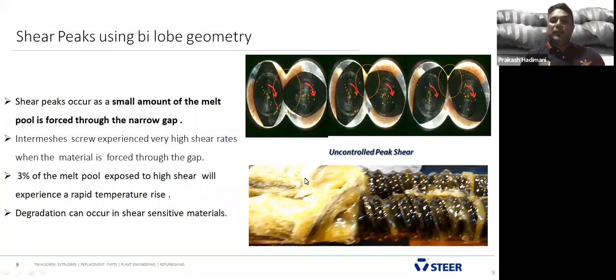Below, there is one example we have given in this photo. It's completely degraded polymer at the end of the screw tip, because initially we thought we were going to get good quality material, but because of the peak shear, every rotation it starts picking up and forming yellow black specks.